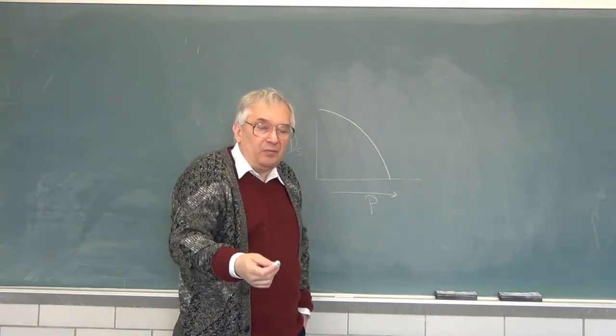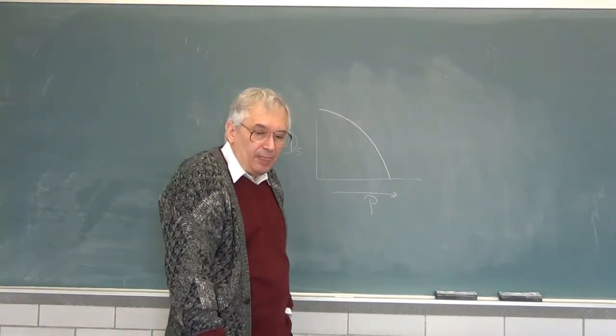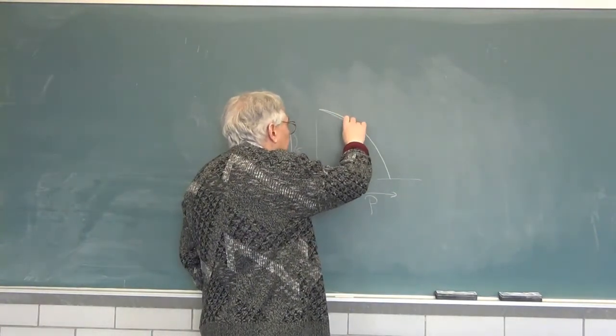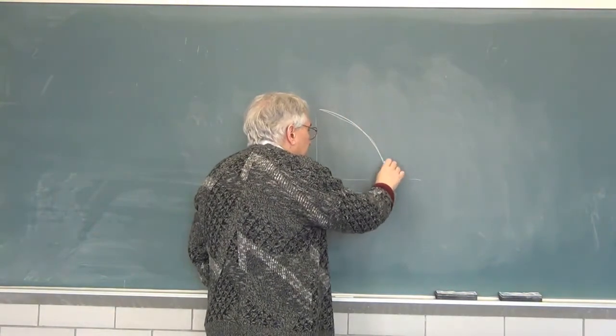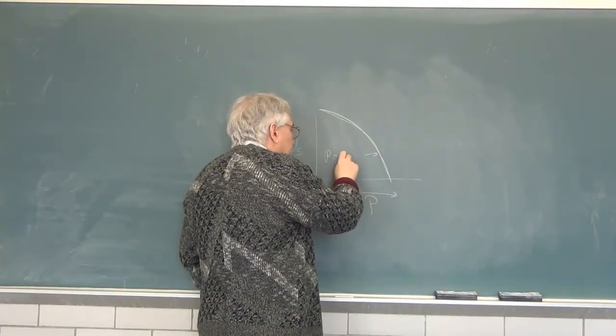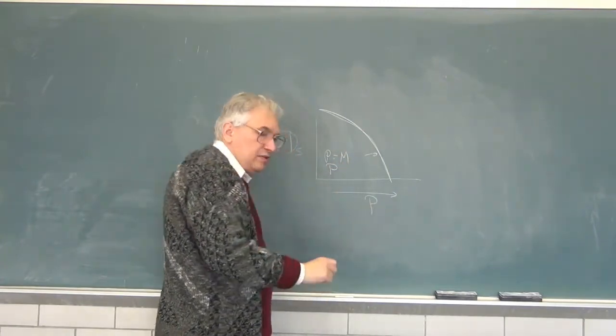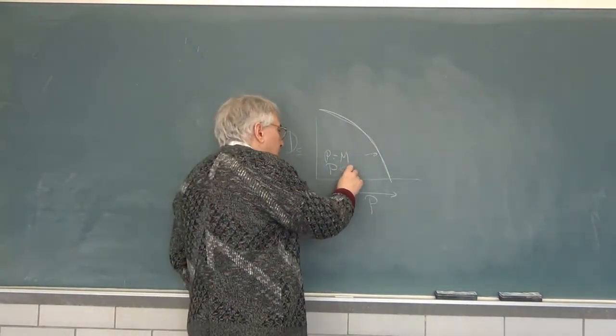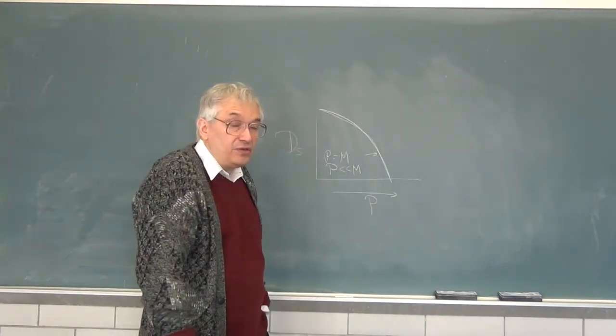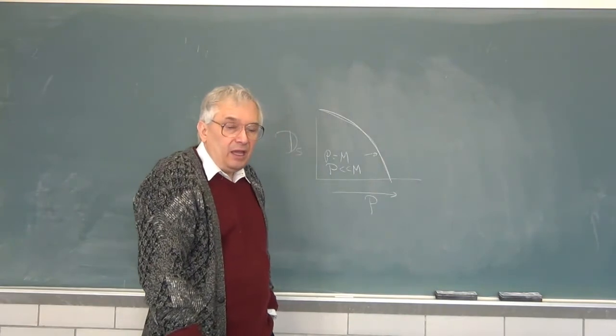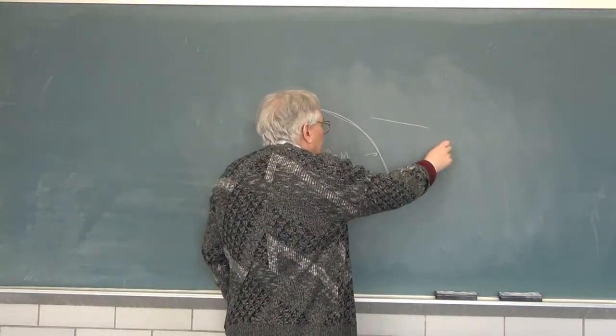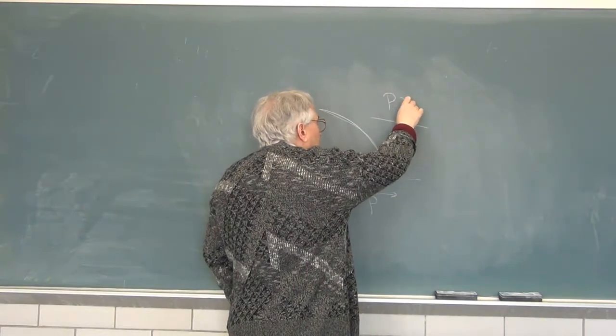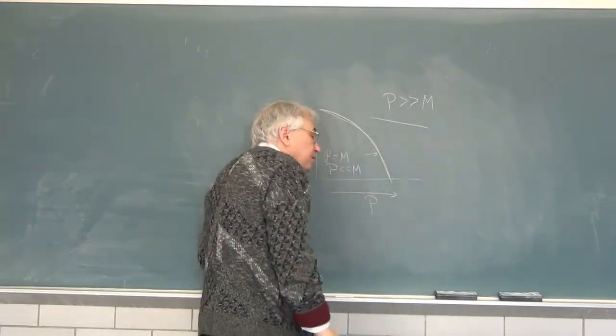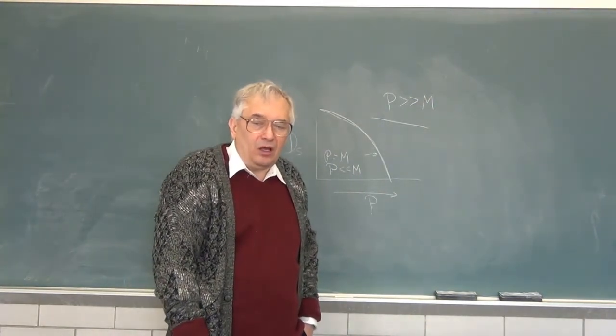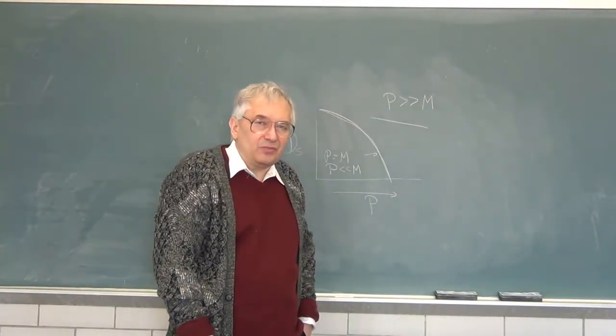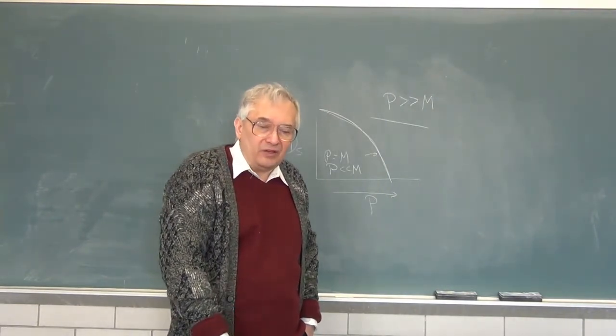And we have, as seen in the figure, a curve showing self-diffusion, meaning the probe and matrix are the same molecular weight. And we have another curve which is very, very nearly the same. So we have a P equals M curve, and we have a case where the probe is much smaller than the matrix, and we see about the same probe behavior. And finally, we have some isolated points up here which sit on a power law which correspond to the probe much larger than the matrix. As you realize, there are only a certain number of points you can fill in to a certain extent.